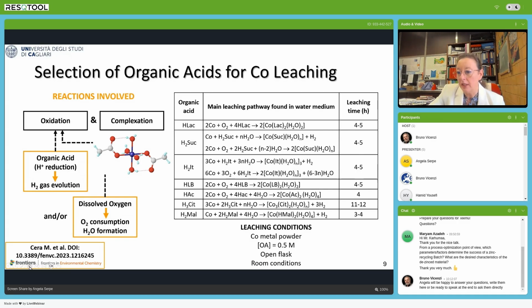In this table on the right, you can see the behavior we observed by reacting cobalt with a selection of organic acids. You can see that in some cases the reaction occurs in the presence of oxygen, and in other cases the reaction doesn't require the presence of oxygen and produces instead hydrogen as a product.